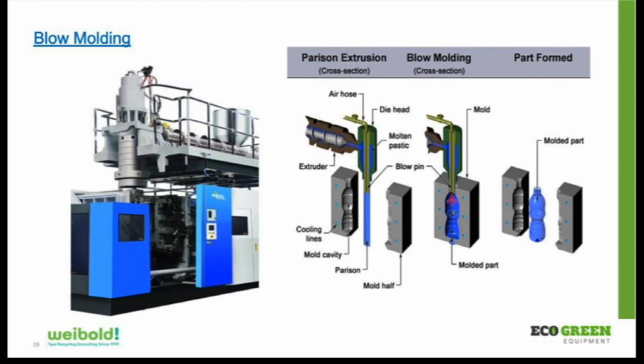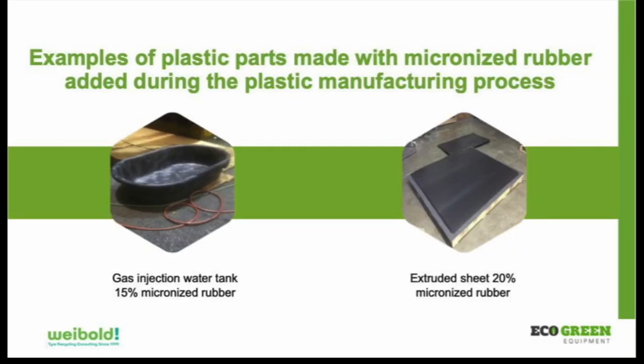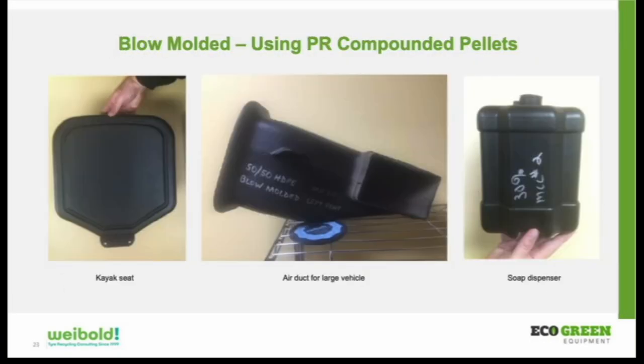The interesting thing about when we add the micronized rubber to the pellet is that the parison stretch is very consistent. Don't know exactly why. We just know that the rubber seems to balance out the parison as it's coming down. So it's a real advantage. One of the disadvantages is the material cools very quickly. So think of it this way: if it's 50% rubber, 50% plastic, the rubber's not melted. So all you're really cooling down is the plastic content. So there are some adjustments that need to be made in terms of how long you leave the part in the mold.